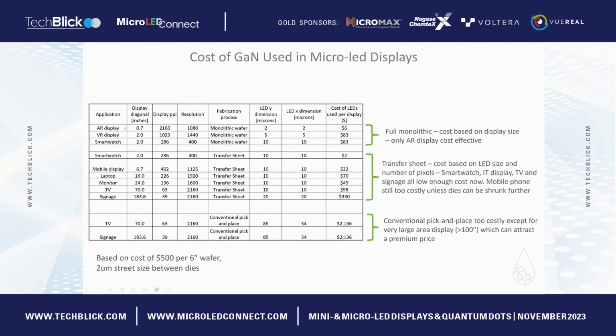And so from a cost benefit perspective, this is just showing a calculation of the different types of displays with PPI and resolution. If you're using the whole of the monolithic wafer, then for something like a smartwatch at 2 inches diagonal, it would be about $83 worth of gallium nitride. But if we use the transfer sheet approach where we spread the LEDs out a lot further, it would come down to roughly $2 worth of gallium nitride. So it's a big reduction by using this chip-first approach, not on the wafer.